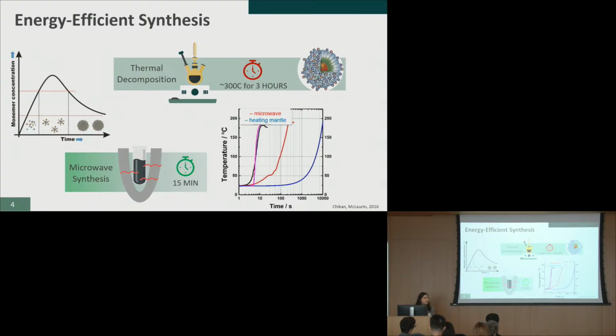So just like how a microwave would heat our food from the inside out, microwave synthesis for nanoparticles is going to heat individual particles rather than heating the entire external system. So over the past couple of months, I've been able to create the same standard of nanoparticles with very similar properties and similar catalytic activity as traditional synthesis in under 15 minutes. Sometimes these particles can nucleate and grow in just 5 minutes.